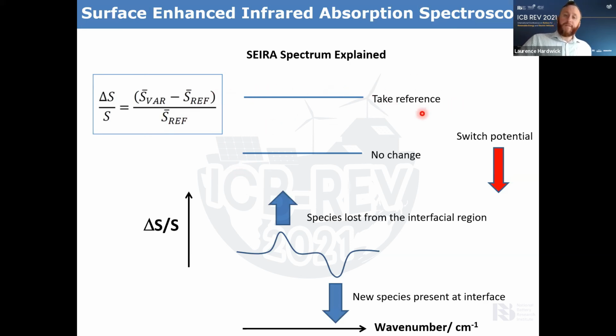When we do our infrared spectra, we take a reference and then we subtract, and so our first spectrum at our open circuit potential should be a flat line. We haven't done any variations, and then we start to switch potential, and if there's no change at the interface, our subtracted spectra shouldn't change. But at a certain point, when we get to the redox peak, or we start changing the speciation in the double layer at the electrode surface, we'll start to see positive going peaks, which are defined as species lost from the interfacial region, and negative going peaks, which indicate a new species present at the interface. So when we start to see these types of features, this indicates a change in the speciation at the interface.